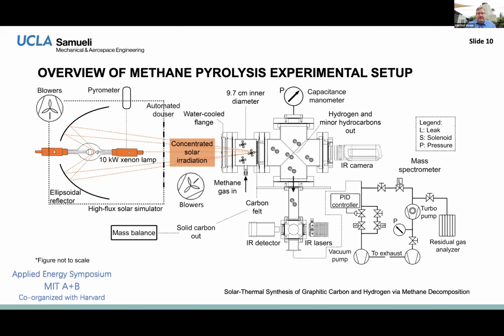This is the schematic of the system, and I just want to point out a couple of things. Here's the source, but we have to go through a window, and we have to water cool that window. That's quartz, and then we hit a target. This is very important. Instead of doing some kind of suspended particle flow, fluidized bed type of reactor, this is actually hitting a thin target. This target's usually about 3 millimeters. It's porous. I'll talk more about that later.